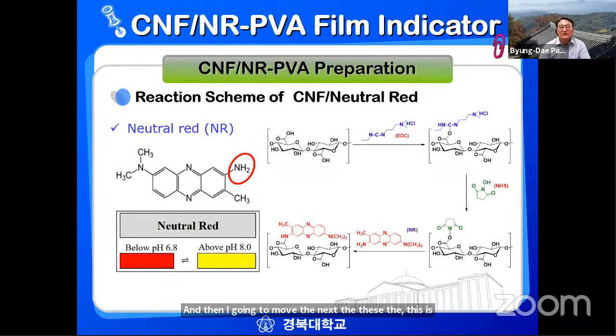And then I'm going to move to the next topic. This is a cellulose nanofiber, which is prepared by TEMPO oxidation and then mixed with neutral red, which is also a kind of pH indicator, and then mixed with polyvinyl alcohol as a matrix for making films. Neutral red has amino groups, so we don't need to activate this pH indicator. As you know, neutral red becomes yellow above pH 8.0, and red below pH 6.8. We use the same scheme, EDC and NHS as the intermediate product, and then make a reaction with neutral red. We expect that the nanocellulose reacts with the amino groups of neutral red to form amide groups. That's the idea.